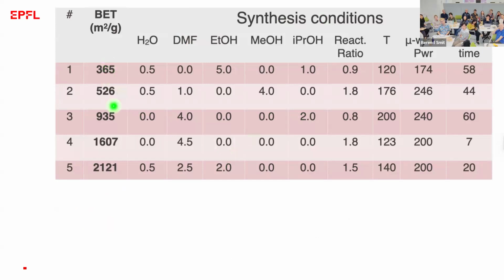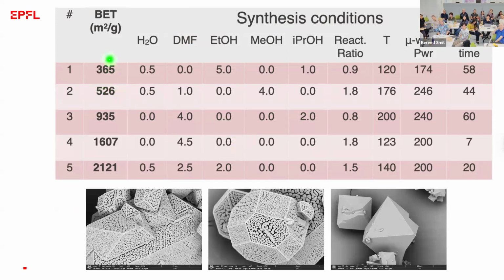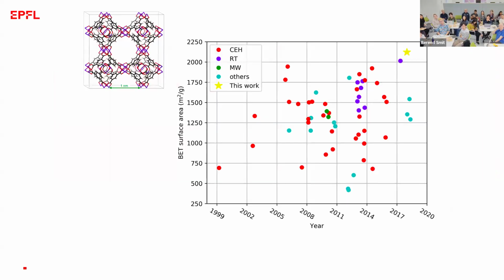And what you could see is, depending on the experimental conditions, there was a large variation, and we got a very large number. And basically what you see, something was happening at the surface. We had no idea what, but this one had the highest BET. And okay, so now what you then typically do, you say, I have the biggest number in the world, and you declare victory. And we now have 41 successful recipes.